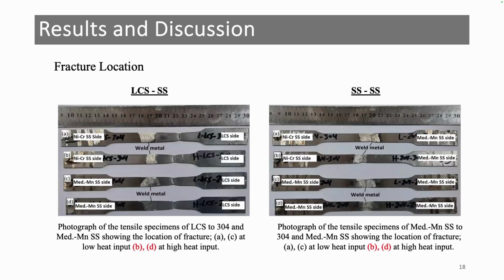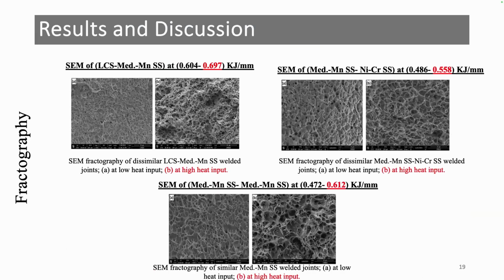And here is the fracture location. In the low carbon steel welded joints, fracture happened at the low carbon steel side. However, in the stainless steel joints, the fracture happened at the weld zone, meaning that the weld zone had lower strength than the base metals. For the fracture surface, there was no big difference. Most of the specimens gave ductile fracture.